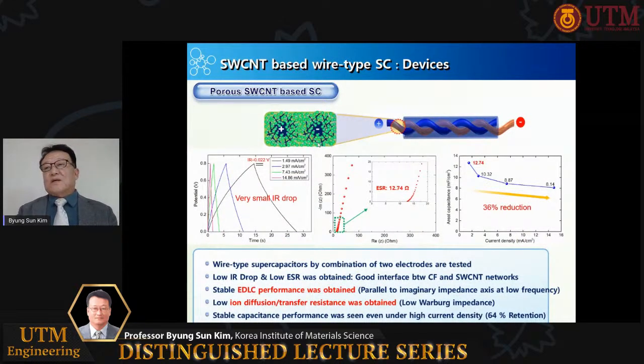Wire type supercapacitors by combination of two electrodes were tested for use as a device. As a result, low IR drop and low ESR were obtained, which showed a good interface between carbon fiber and the single-wall CNT networks. Stable electrical double-layer capacitance performance was obtained that is parallel to the imaginary impedance axis at low frequency. Low ion diffusion and transfer resistance was obtained, which is low Warburg impedance. Stable capacitance performance was seen under high current density, with 64% retention.